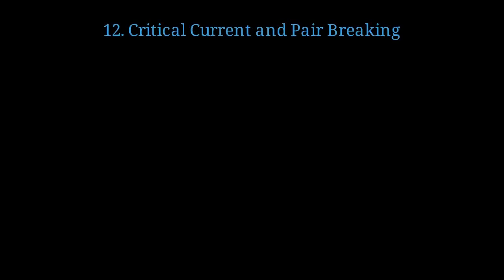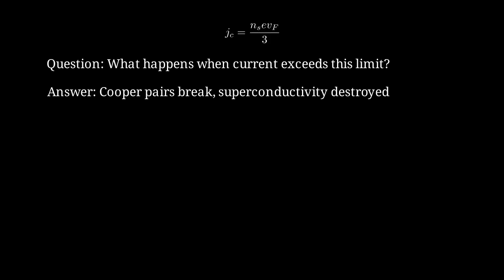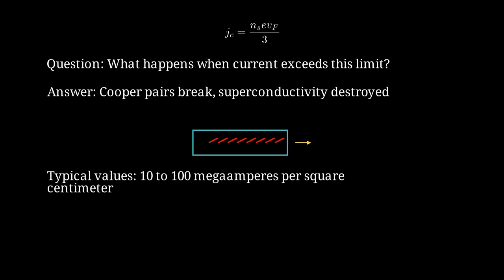BCS theory explains the maximum current a superconductor can carry. The depairing critical current density is roughly Ns e v_F over 3, where Ns is the superfluid density. What happens when we try to push more current through a superconductor than this critical value? Above the critical current, the kinetic energy becomes large enough to break Cooper pairs, destroying the superconducting state. When current density is too high, pairs break apart and the material returns to the normal resistive state. For thin-film superconductors, critical current densities can reach 10 to 100 megaamperes per square centimeter.